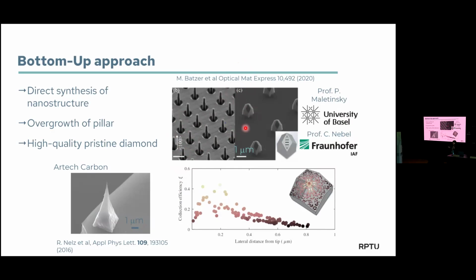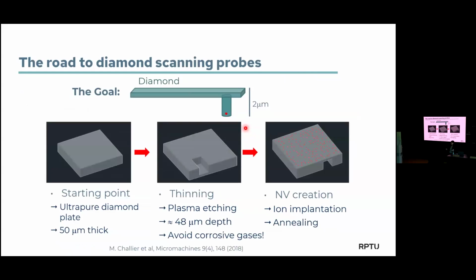So depending on how you approach this, you get out a different structure, but still it's very hard for us to make the color centers at the tip of this pyramid, because when they are made during the growth, they will be everywhere in this growing diamond. So at the moment, as far as I know, all the results that you see are still obtained not with this bottom-up, but with a top-down approach. And then in the end, what you want to do is you need a diamond pillar, more or less cylindrical structure.